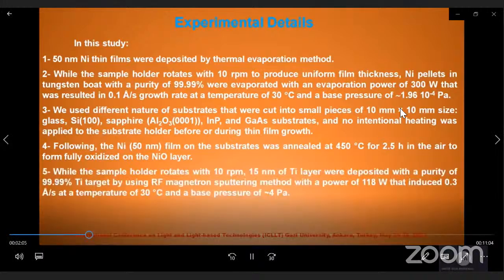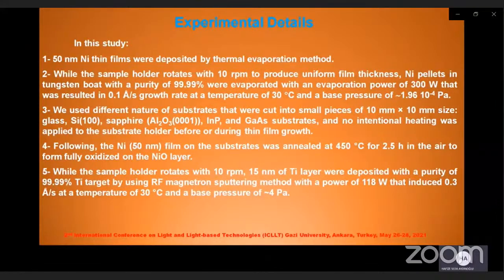While the sample holder rotates at 10 RPM, a 15 nanometer titanium layer was deposited from a 99.99% purity titanium target by using RF magnetron sputtering with a power of 118 watts that induced 0.3 angstrom per second at a temperature of 30 degrees centigrade and a base pressure of approximately 4 Pascal.